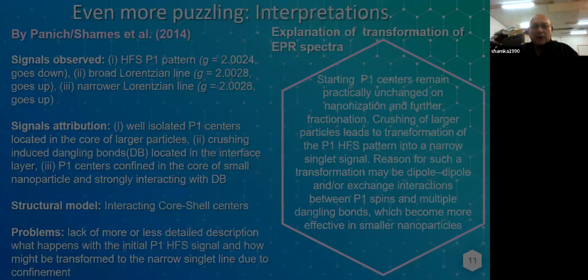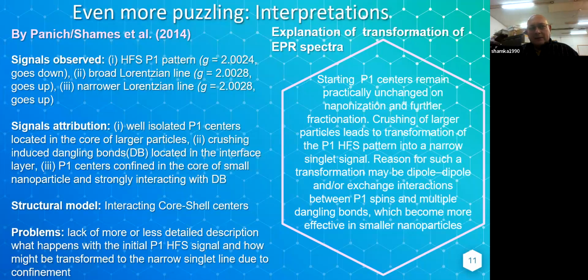Interesting. Let's go further. Except for the experimental facts, the most puzzling are the interpretations. In 2014, this is a short summary of signals observed: the P1 pattern, hyperfine P1 pattern, broad Lorentzian line, and narrow Lorentzian line. This is an attribution: well-isolated P1 centers located in the core of larger particles provide the P1 signal. Crushing-induced dangling bonds are located in the interface layers. And the third signal, which is also a singlet with no hyperfine structure, is located with the same G factor as dangling bonds.